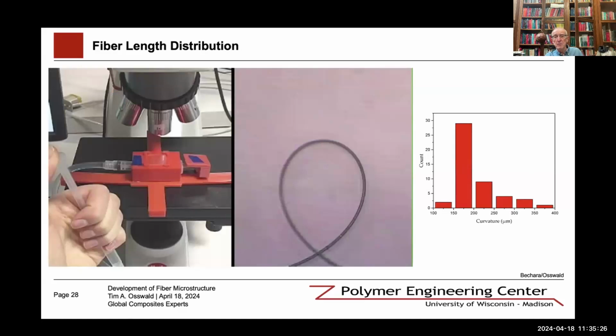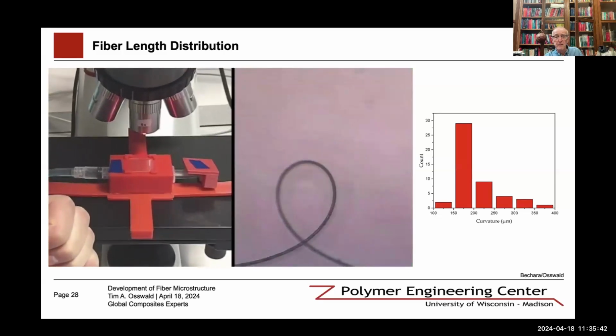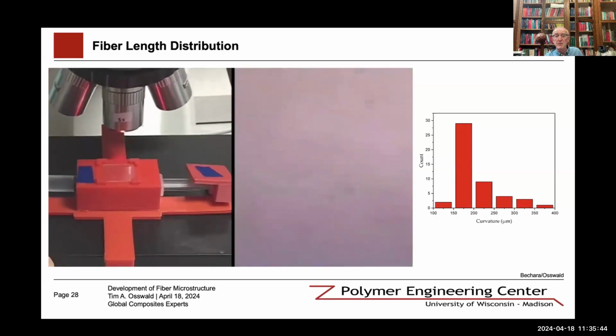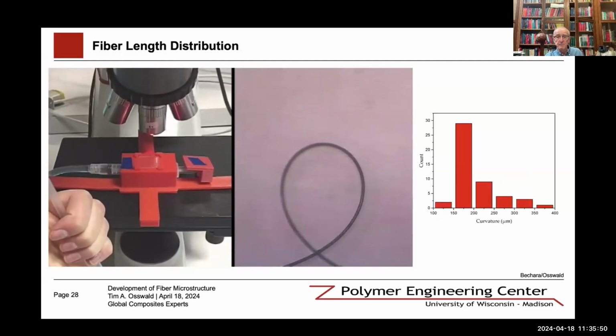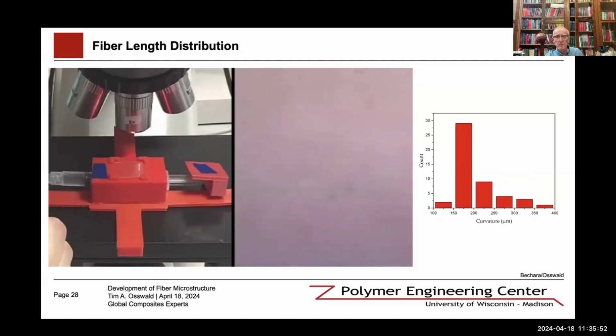So let's look at what causes fibers to break. There are some experiments that my graduate student Avran Bechara did, where he made a loop of a 19 micrometer diameter fiber. By pulling the fiber, we can measure, and you can see the breaking of the fiber at the end. So he recorded the point where the fiber broke.